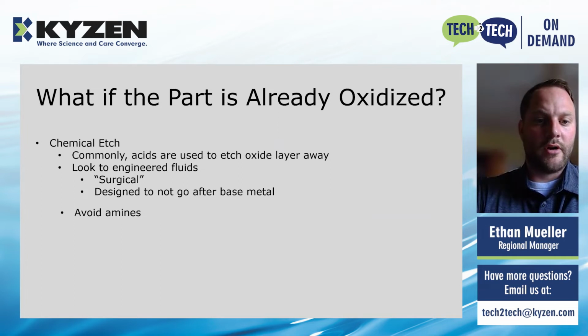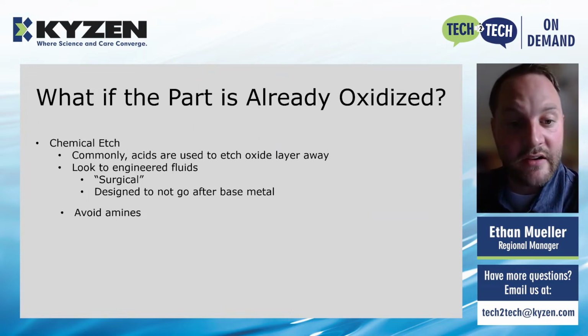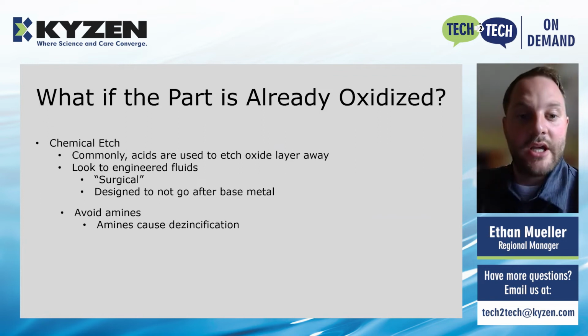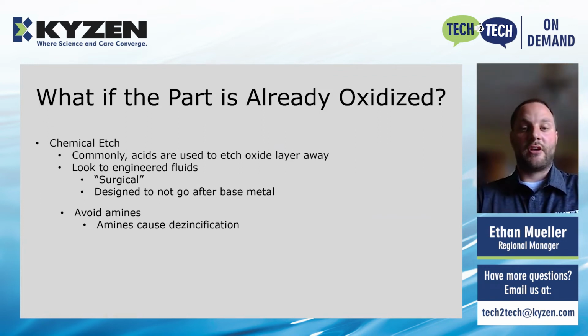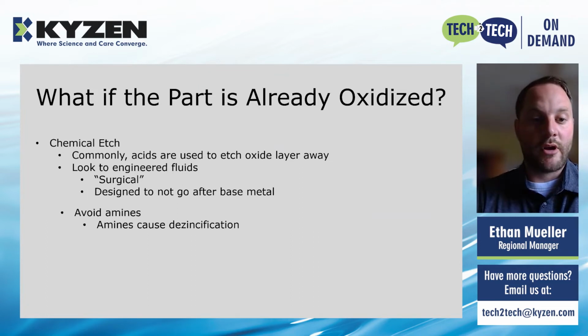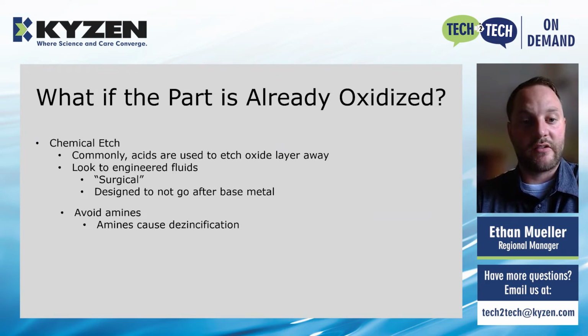When we are looking to etch our parts, we want to avoid amines when we're dealing with brass and bronze if it has zinc in it. Amines extract the zinc from the surface of the part, and that's actually causing dezincification of your yellow metals. And so we want to avoid amines at all costs. And a lot of products out there, a lot of cleaning products and stuff have these functional groups in them. So just be aware of that.